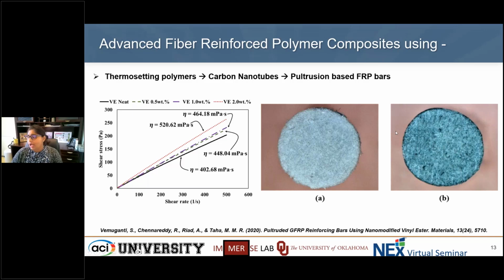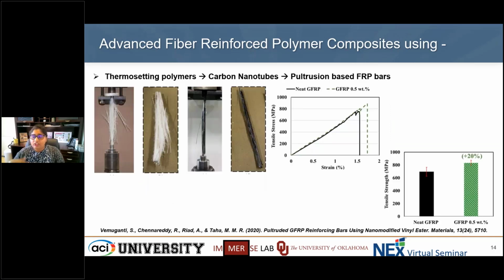If you see this picture here, you have the plain pultruded bar without any fillers or carbon nanotubes, and you have this right section with carbon nanotubes. So you see some spread of the carbon nanotubes through the section of the bar itself. Trying to understand the mechanical properties, doing a tensile test, we achieved about 20% improvement in tensile strength. If you look at the failure mode, from a brittle, very explosive kind of fibrous failure, which is broom type as described in ASTM, we see a lesser broom or a less explosive kind of failure in the FRP modified with carbon nanotubes.